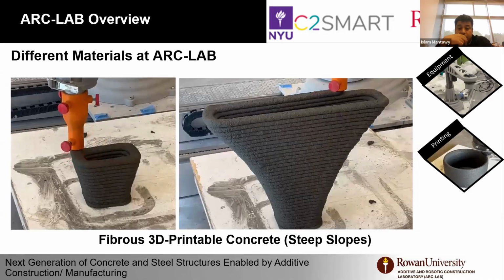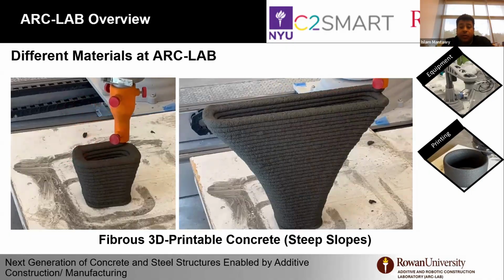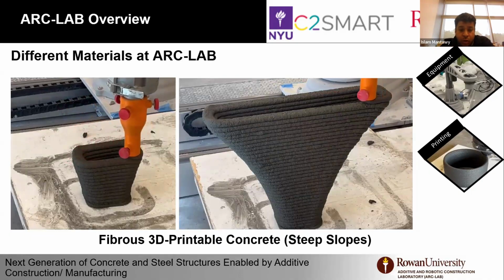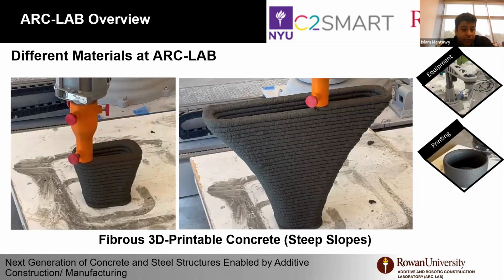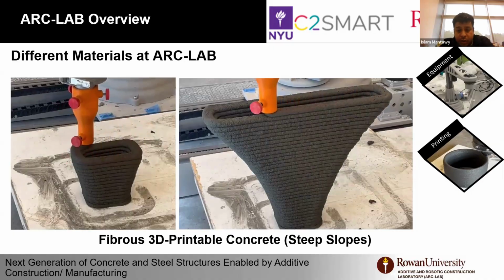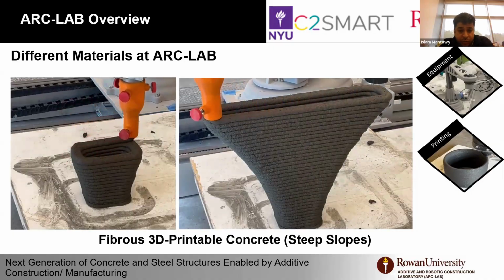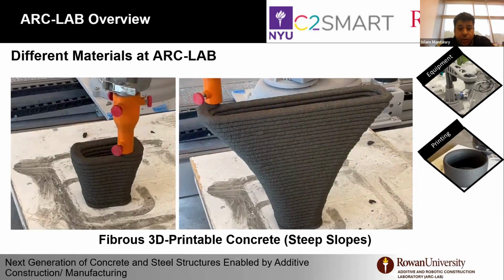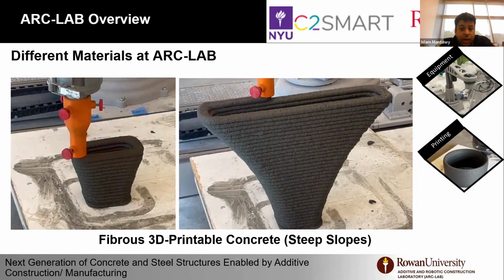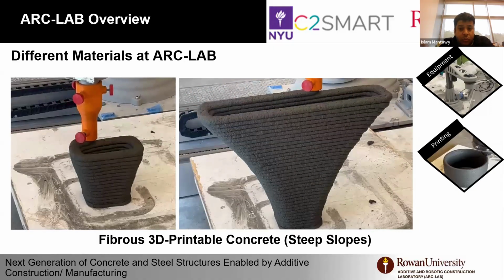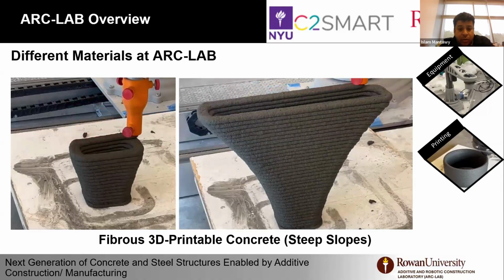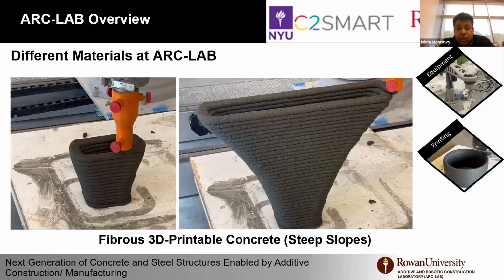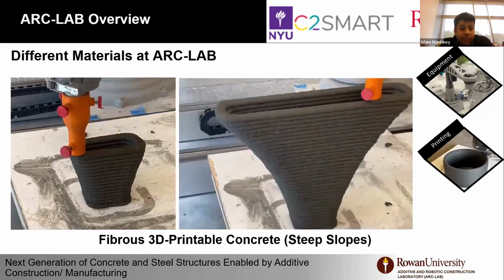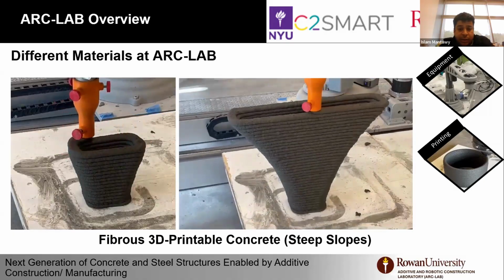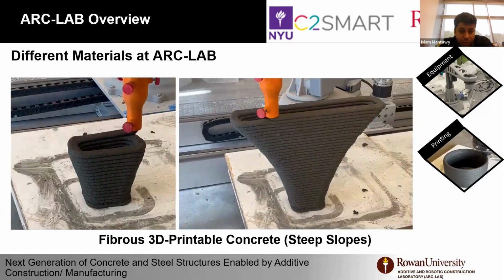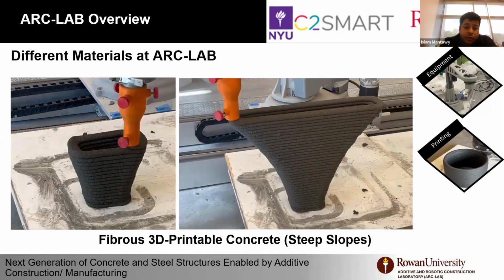We are also trying to examine printing an even steeper slope. With and without fibers, we were able to achieve 45 degrees stability from vertical position for mixes without fiber. This number increased to 65 to 70 degrees from vertical position with fibers, which is a very steep slope. As I mentioned, we are not using any accelerant in our mixes. So our mix is called one component: whatever you mix, you pump, you get at the nozzle. However, there are other systems that use injection of accelerant that accelerates the setting immediately at the nozzle level, which is called 2K, which we are not using. We have the capability, but most of our research is done with 1K.